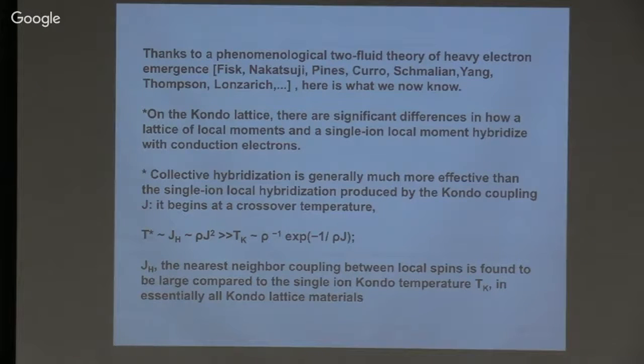How did we find our way into this problem? It was, again, phenomenological. By 2003, we had a terrific set of new materials called the 115 materials: cerium cobalt indium-5, cerium rhodium indium-5, cerium iridium indium-5. And you could begin to play with them as a function of doping and pressure. And the great thing about them is they are really clean. You can easily make a sample which is as clean as the very best cuprates, which might take you years to figure out how to make. They really make pure samples very easily.